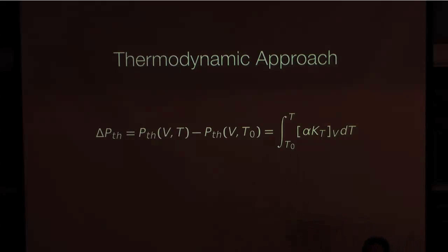But there's a rescue that people found in the 80s, and it was fine in the 80s and 90s literature, but don't do it anymore. Nevertheless, I'll tell you what it is. Think about the temperature effect, for example. If you heat it up, the material softens, so this value, K prime, goes down. If temperature goes up, alpha goes up, right? So this one goes down, this one goes up. They could offset each other.